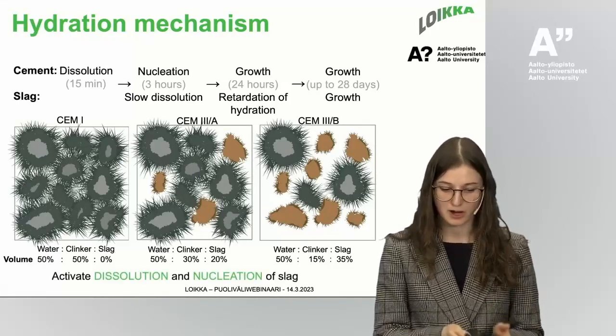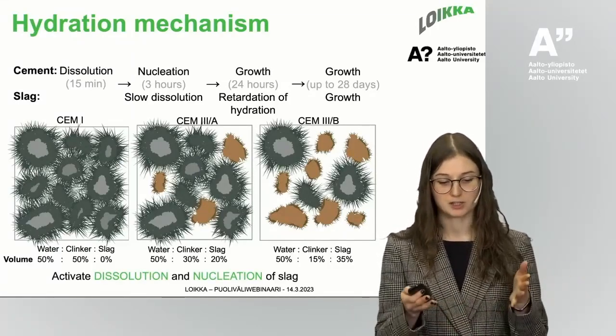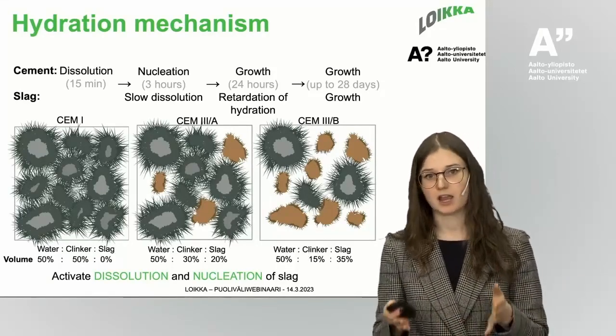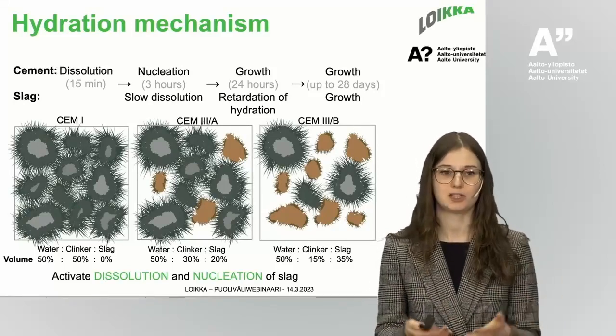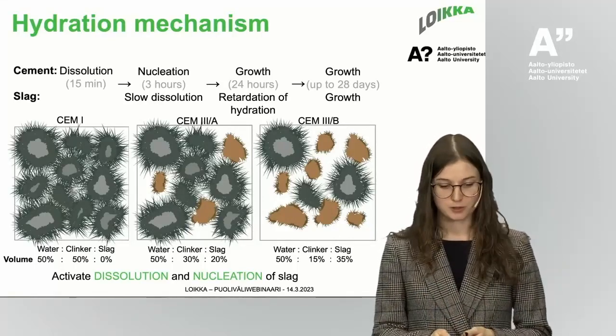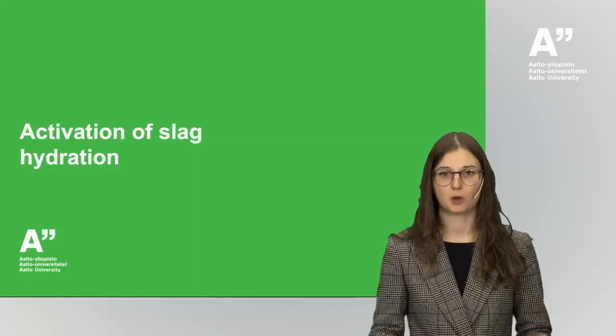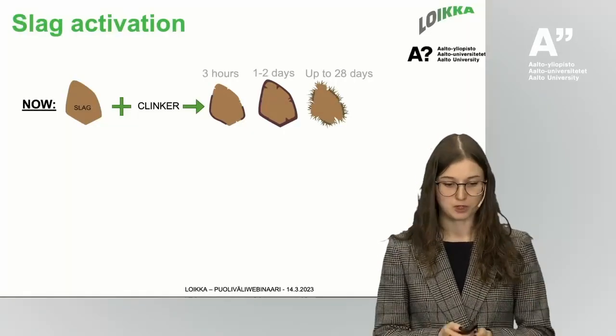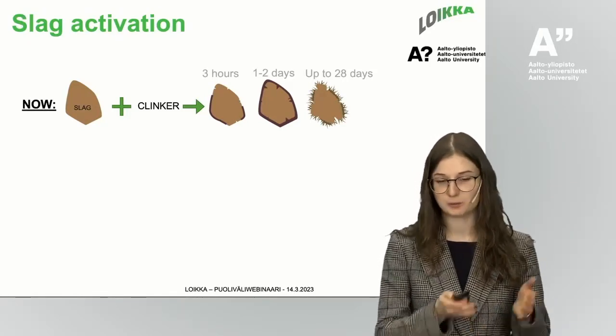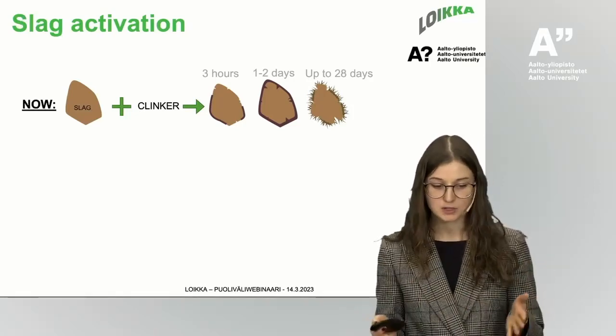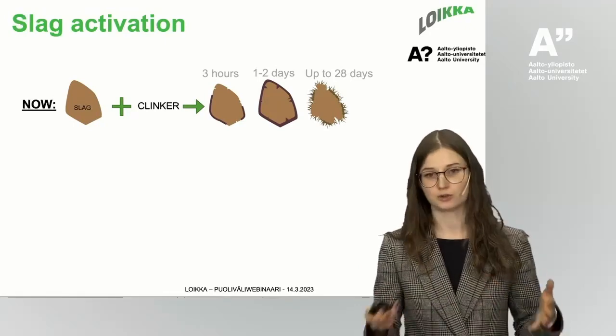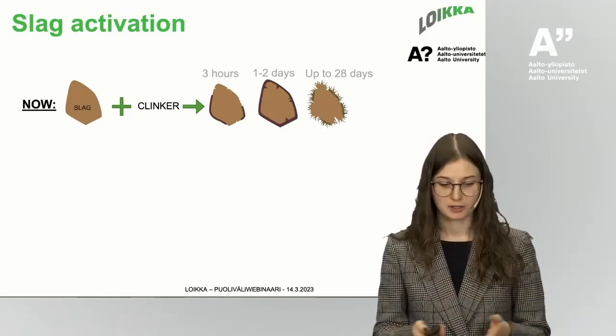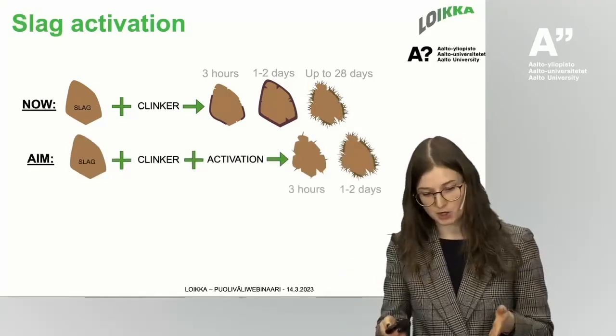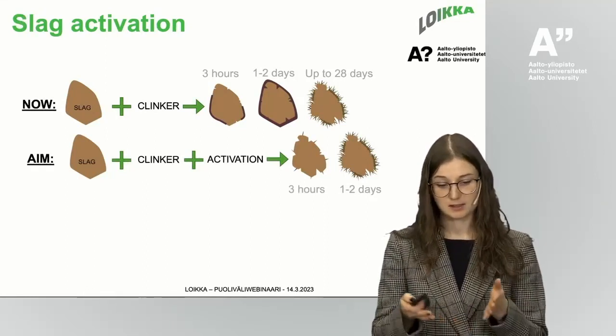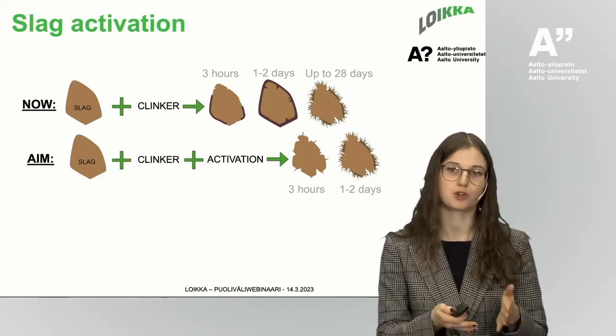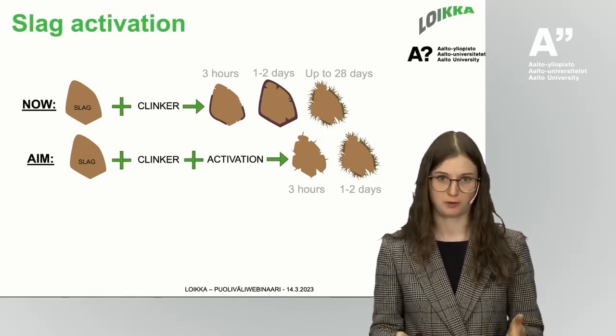So the things that we are trying to affect in this sub-project are the dissolution of the slag and the nucleation of hydrates on the slag. So it starts producing hydrate, it starts helping bind everything together. For that purpose, we need to activate the slag, activate those two mechanisms. So far, just a small recall of what is happening now: we have only slag and clinker. In the case of slag, it gets this passivation layer in the first days, it's not hydrating, and then the hydration is happening at the later days. But we want to do some activation steps so that the dissolution starts earlier within the first day, and the hydrates also start growing within the first days.